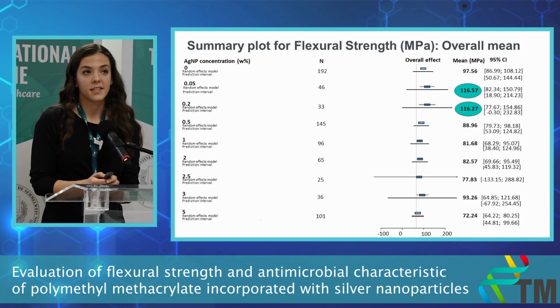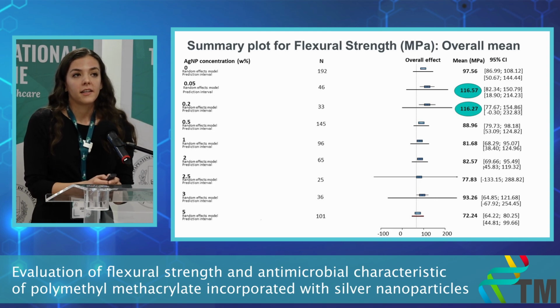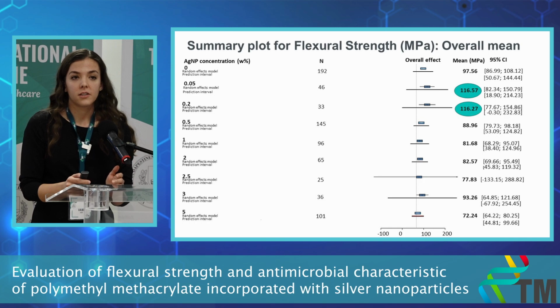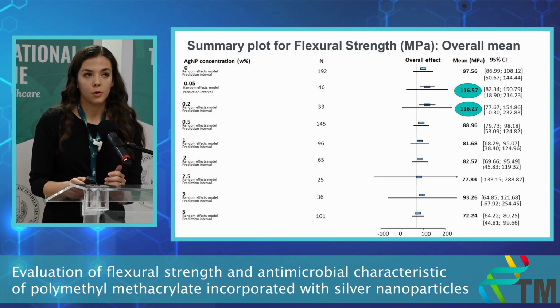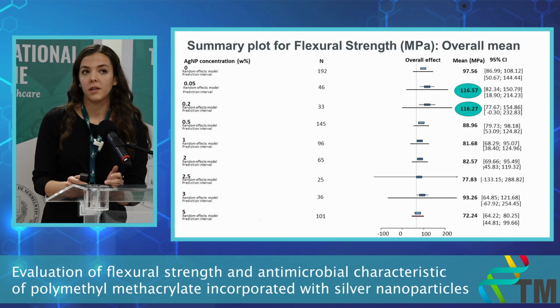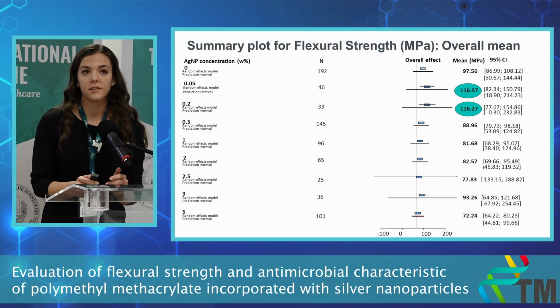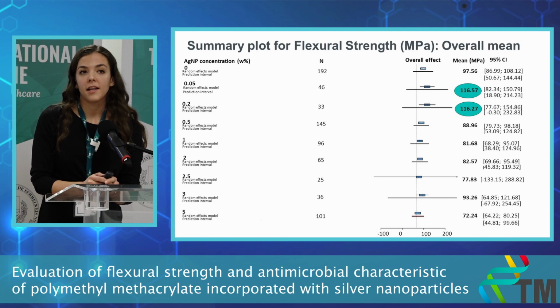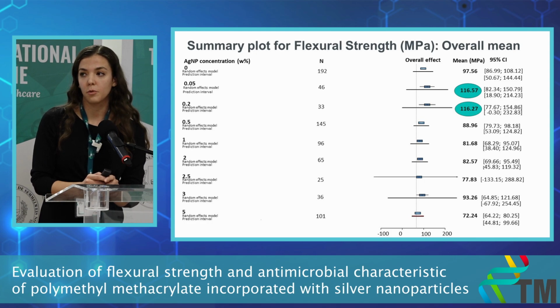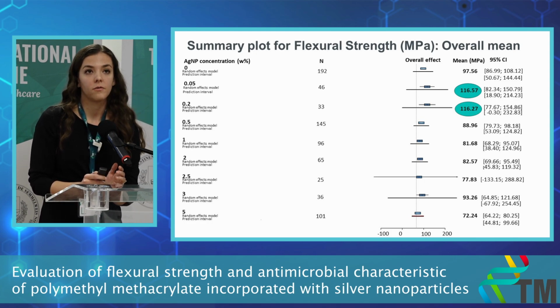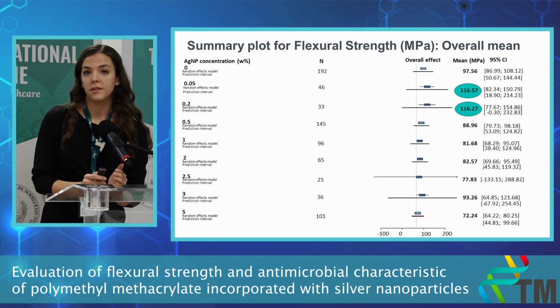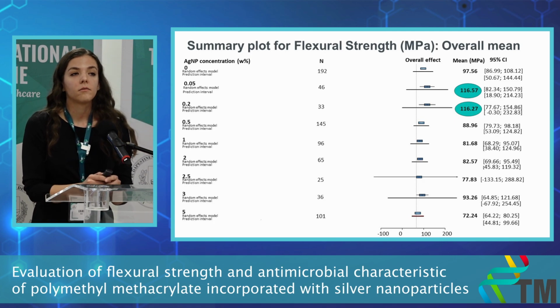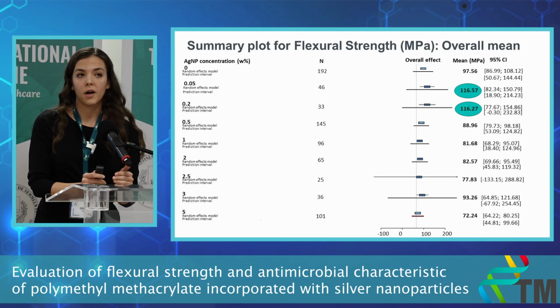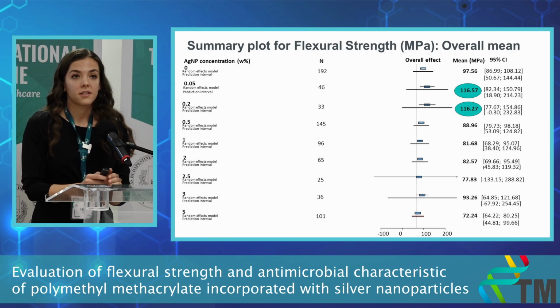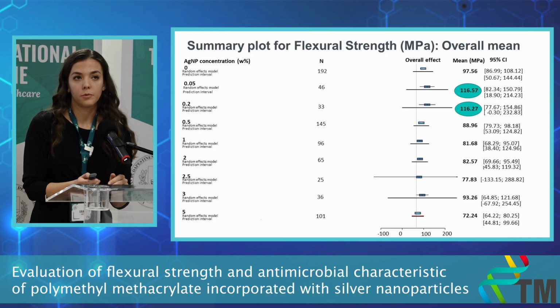You can see here my summary plot. On the left, you can see the concentrations, or the percentages, of silver nanoparticles, and on the right, the overall mean of flexural strengths for each concentration. I have highlighted two concentrations, 0.05 and 0.2% of silver nanoparticles, where the flexural strength was higher compared to the control group. And in case of 0.5% or above, the flexural strength was not superior to the control group.